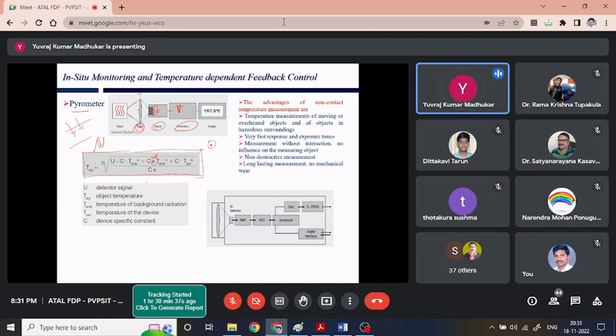Now here one more thing, in case of a pyrometer, another problem comes into the picture: it is dependent on the emissivity of the surface. Now the emissivity of the material changes with respect to the temperature. So yes, it has got a lot of advantages. Temperature measurement of a moving or overhead object can be made, no problem at all. Very fast response time, it can measure without interaction, no influence on the measured object, non-destructive measurement, long-lasting measurement, no mechanical wear at all.